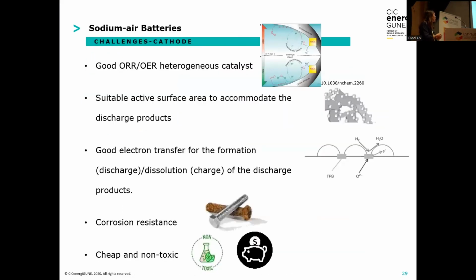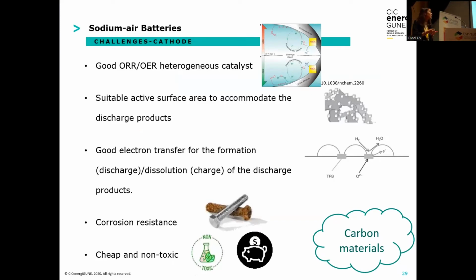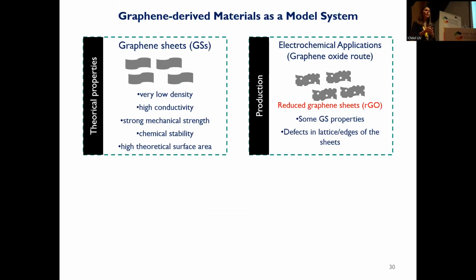And lately, we've been focused here. These are all the requirements that we need for the oxygen reduction and evolution reactions: a really high surface area to accommodate all the discharge products, and electron transfer is really important, and for that carbon materials are a great choice. So we've been focusing for the last 4 or 5 years on graphene-based materials. There have been several talks on graphene. They have very nice properties, but for the production and the electrical applications, what we're using is reduced graphene sheets, where we have these defects, and it is in these defects that the oxygen reduction and evolution reactions are going to take place.